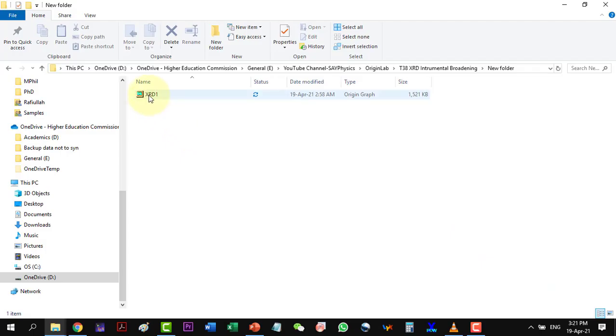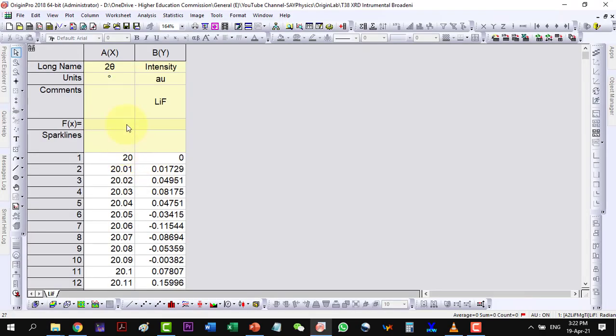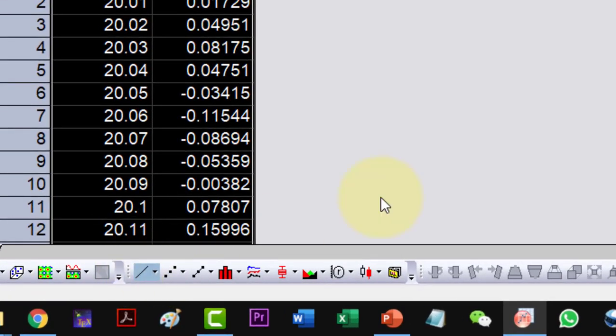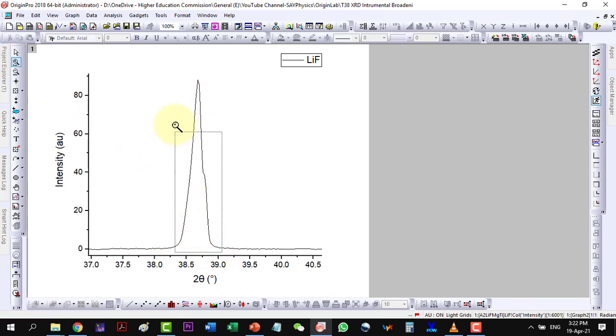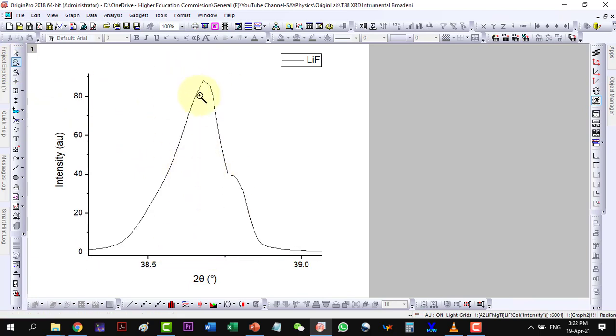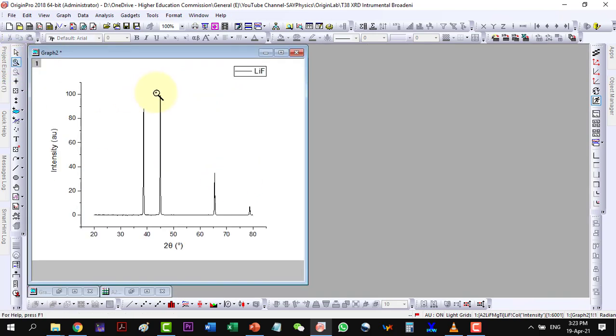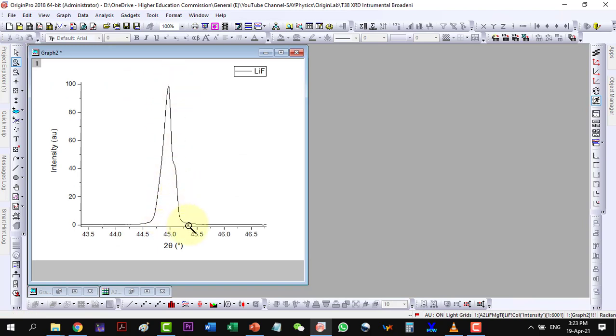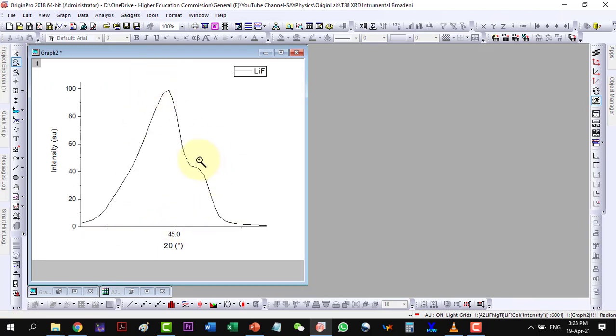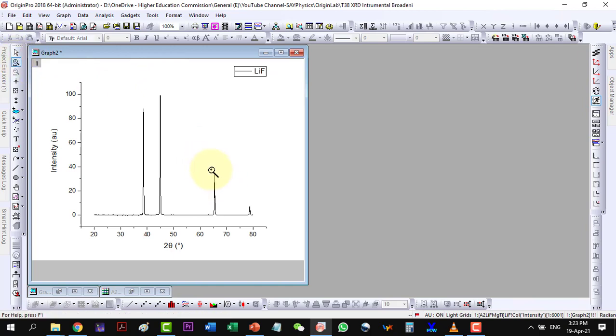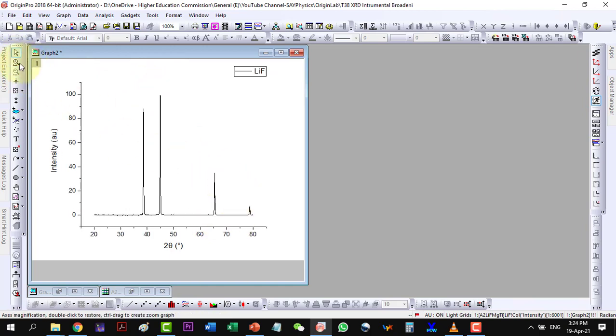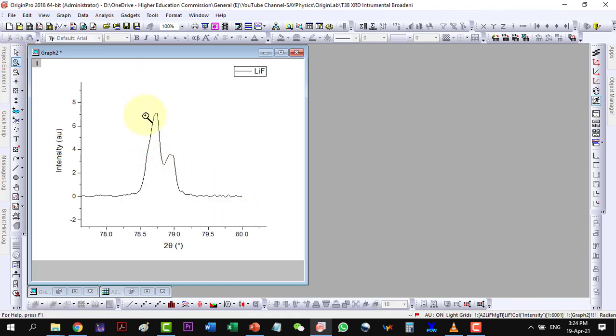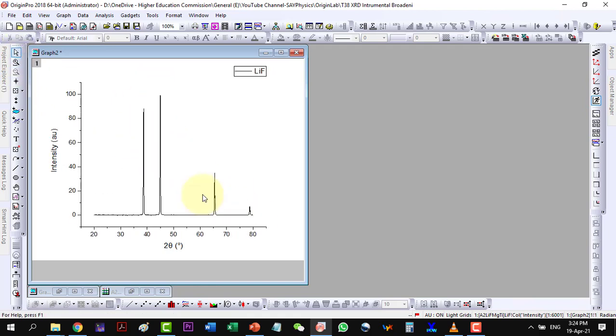How to do this in Origin? Let's open XRD data. This is the XRD data of LiF. Let me zoom each peak in order to check for the Kα1 and Kα2 convoluted peaks. This peak belongs to Kα1 while this shoulder is due to Kα2 contribution. Similarly, in this one, we have the same convoluted peaks, this one as well, and finally here too. We see that the Kα2 contribution becomes prominent with increasing values of 2θ.